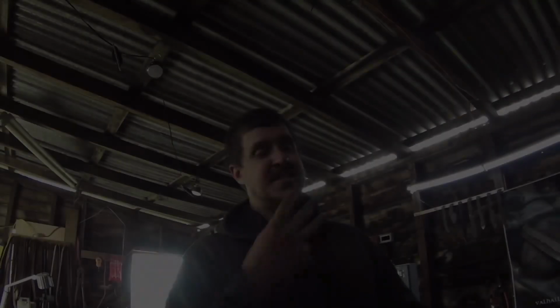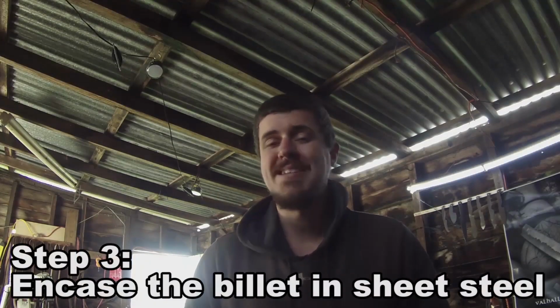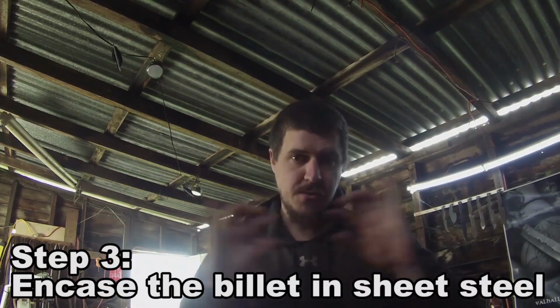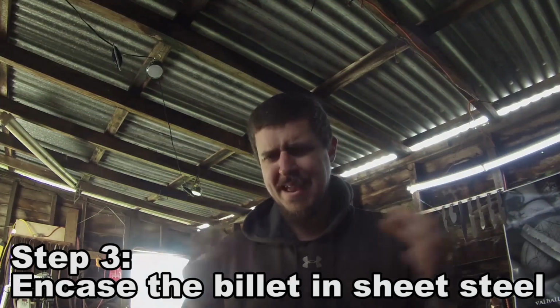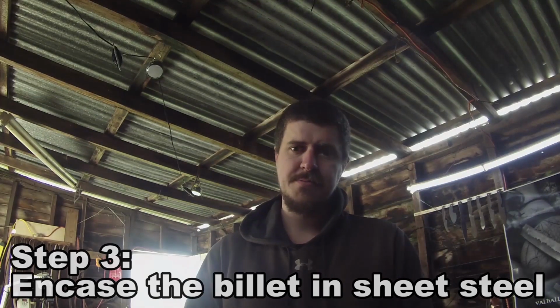Second thing. Step 3. Get some thin gauge sheet steel and seal that billet around. Create a jacket for it, sealing up any and all air holes. So I recommended in the video to put sheet steel down the sides in order to fully seal the billet. Now, fully sealing the billet, I still recommend. Also, not 100% necessary if you're maintaining just brazing temperatures, but it will create that little sandwich sealed packet that will prevent any copper from squeezing out.